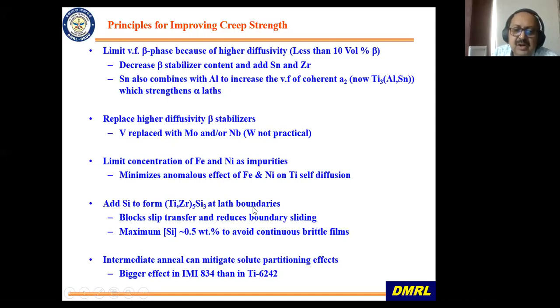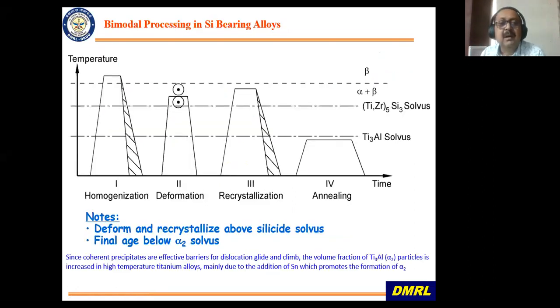Then, as I told you, silicon is used in most of the high temperature titanium alloys because it improves the creep properties by blocking the slip transfer, or restricting the deformation between the laths. I will show you the microstructure of this. And then there is also an intermediate anneal which can improve the creep, but I am not talking about this now. When we talk about titanium in more detail, we'll talk about that.